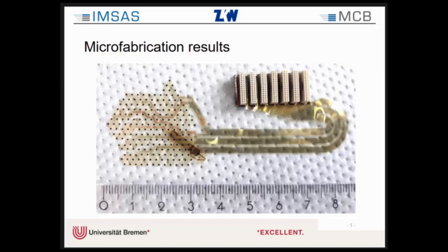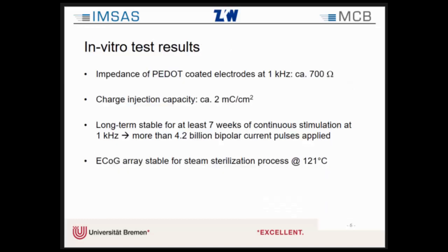So after fabrication, of course, we did some in vitro test experiments to prove the stability. The impedance was measured at 1 kilohertz, which is approximately 700 ohm, mainly due to the serial resistance of the conducting paths and the spreading resistance of the electrodes. The charge injection capacity of the PEDOT coating was measured to be approximately 2 millicoulomb per square centimeter, which is a value comparable to reported values in the literature.